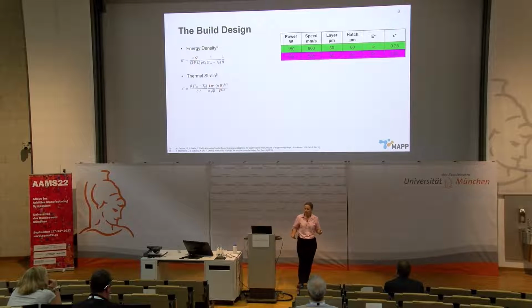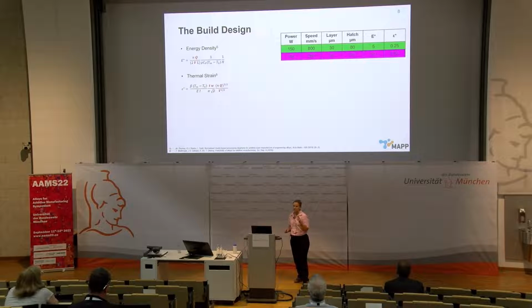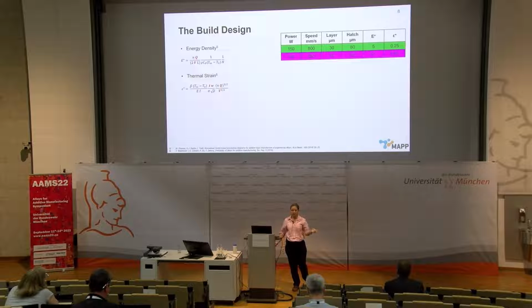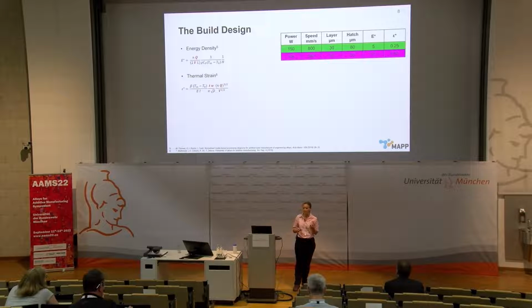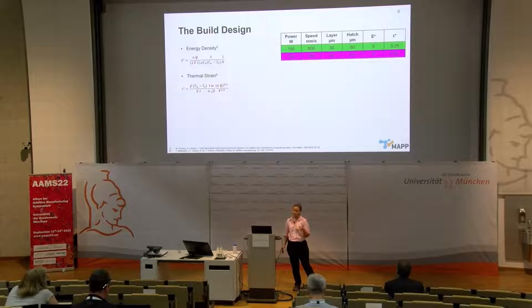So, applying this then to structural lattices, we've got two equations up here on the graph. One is a volumetric energy density calculation, and one is a thermal strain calculation. So these are both available in the literature, and highlighted in red are the key parameters that I'm picking out for this work. So Q is our power, V is our scan velocity, and then we've also got these parameters T and W that appear in this thermal strain calculation.